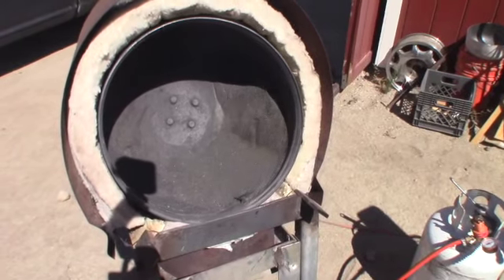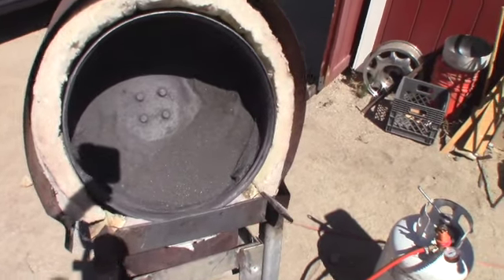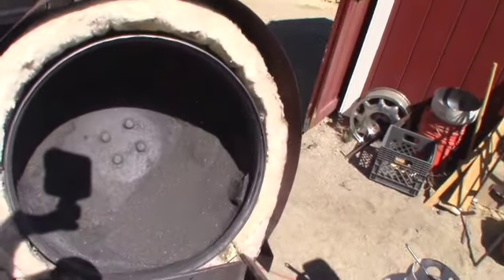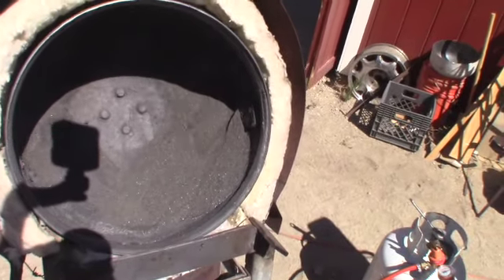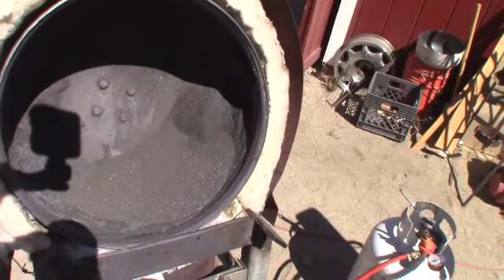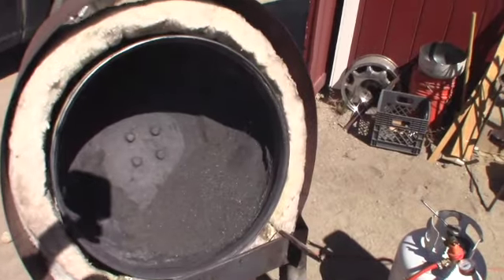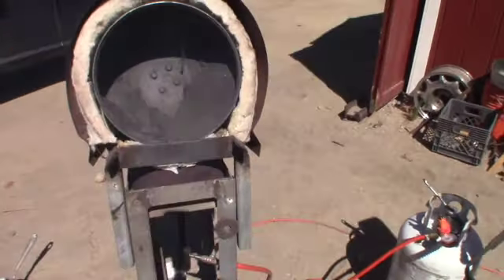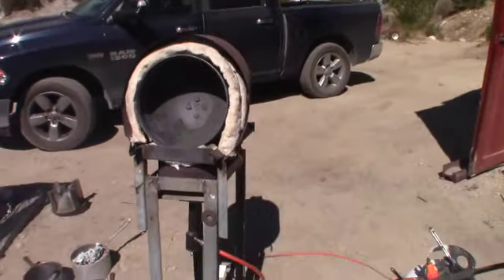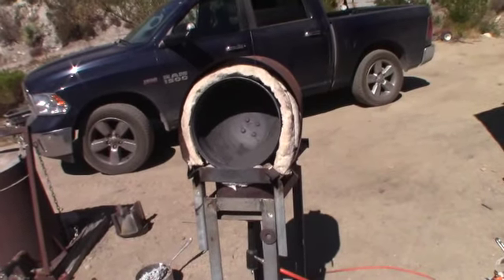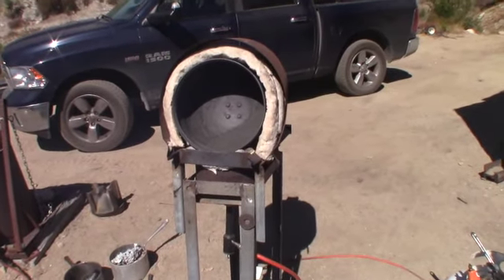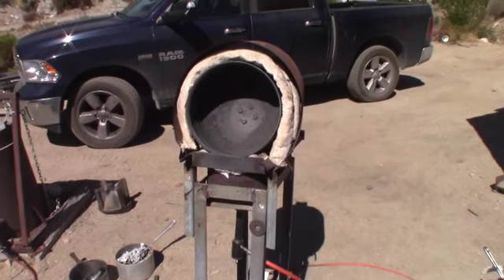And once everything gets roasted, it turns black. So this indicates that the pyrites are gone. You don't have little gold pieces in there anymore. The sulfur's baked away, and it's basically iron, and what trace gold there was will be inside this little roaster here.